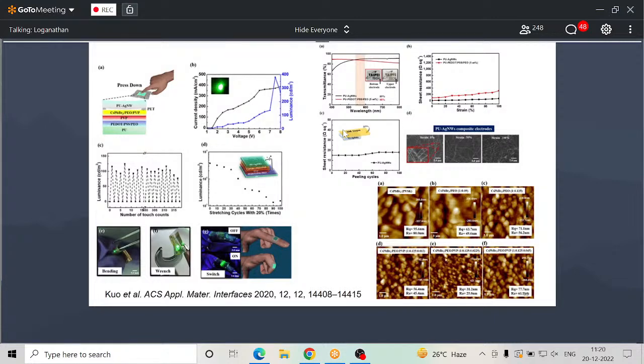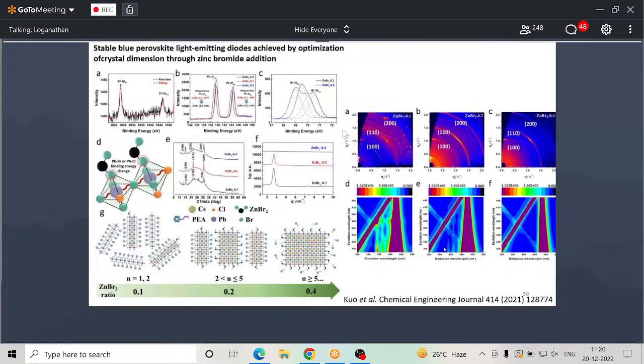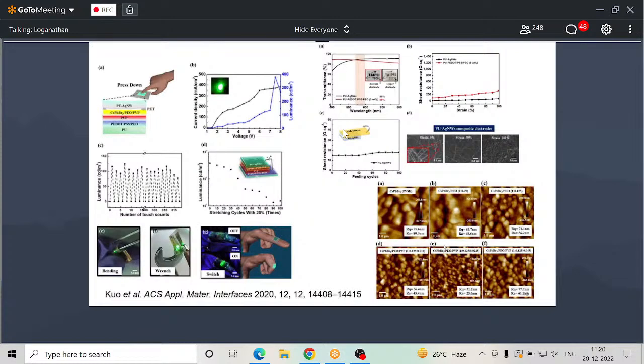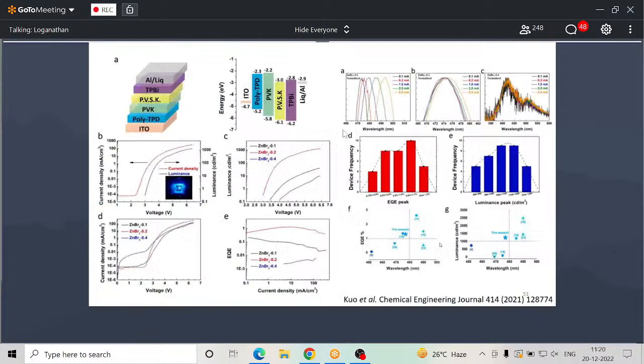And then we also study the roughness characteristics. And this is the other one, because the last three projects we've done on 3D perovskite materials. Now we try to fine-tune our perovskites to 2D structures, because 3D perovskites don't have very good efficiency. In order to improve efficiency, we rely on 2D structures. For that, we use some zinc bromide addition with PEA conventional ligands, and then we tune the zinc bromide addition slowly, stepwise, from 0.1, 0.2, 0.4. So in this case, we can see how the crystallinity is getting enhanced at 0.2. So that means our 2D perovskites are growing at a very good pace.